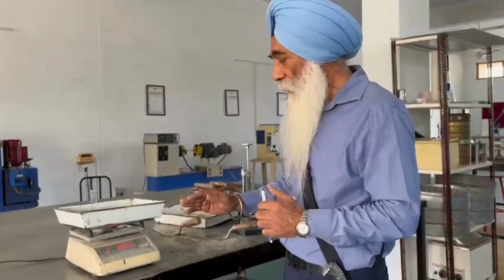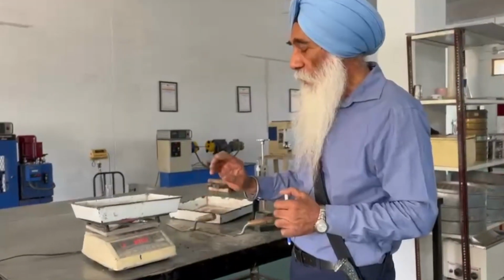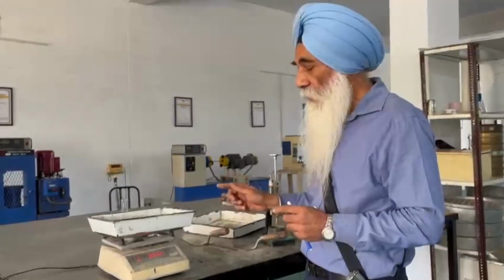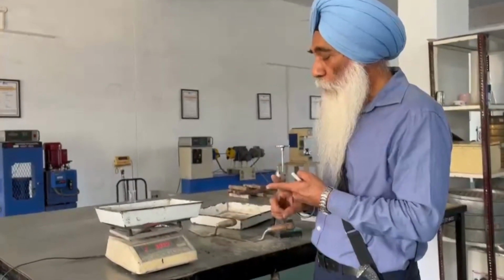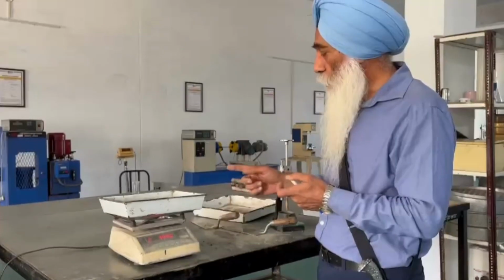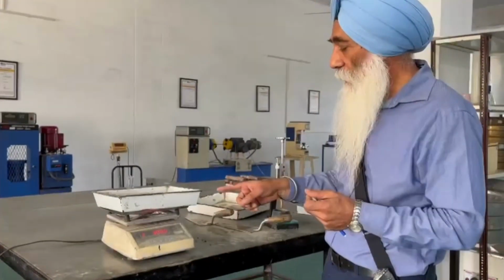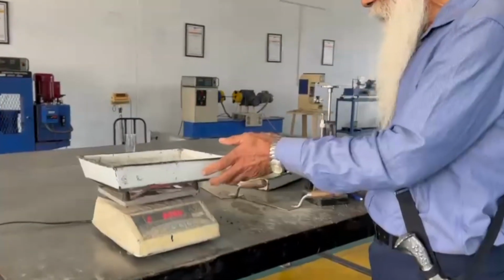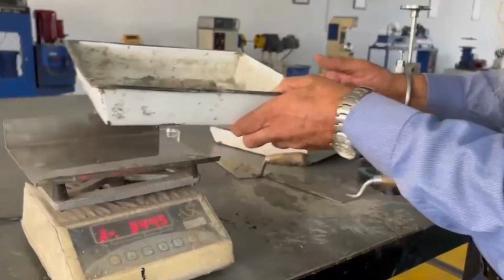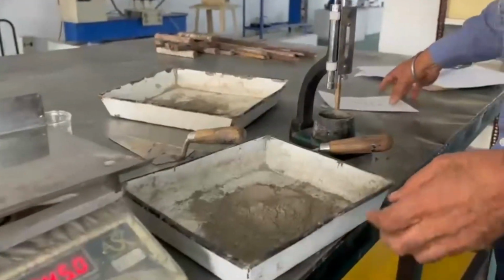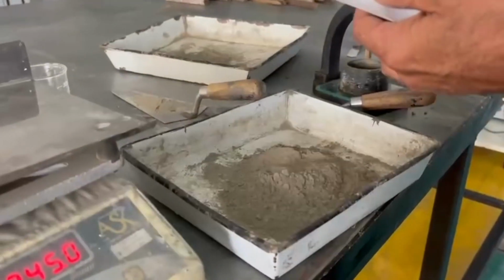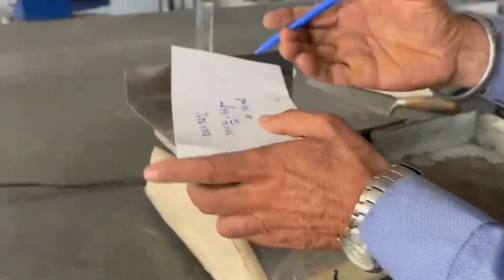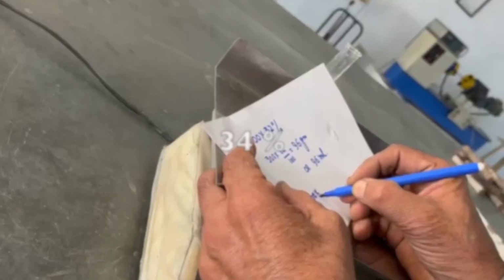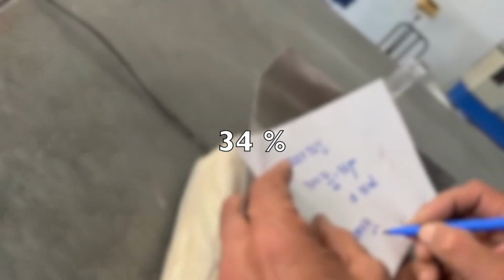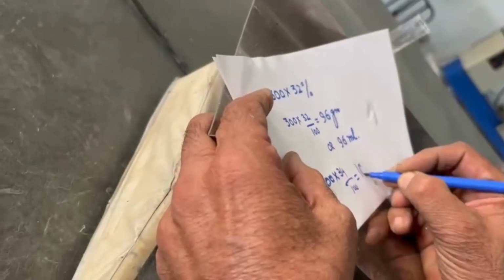Now we can repeat the same process by increasing the percentage of water by 1%, 2%, 3% and so on. So now I have taken again 300 grams of cement. This time I will take water as 34% of the cement. 34% of 300 grams becomes 102 ml of water.